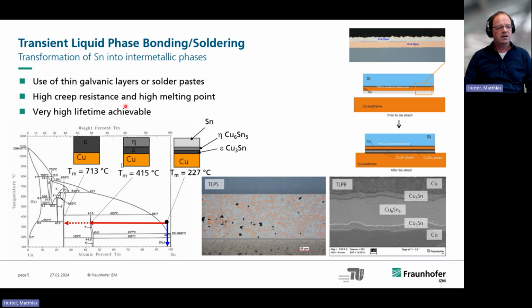You have a higher creep resistance, and you may achieve higher lifetimes, but you have to be careful, because solder normally accommodates the thermomechanical stresses, and this is not possible with intermetallic phases, because they cannot plastically deform. They are more or less brittle. So you always have to bear in mind that if you use the transient liquid phase bonding or soldering, you need to have another material, or you have to somehow allow the system to bend and to accommodate the thermomechanical stresses elsewhere.